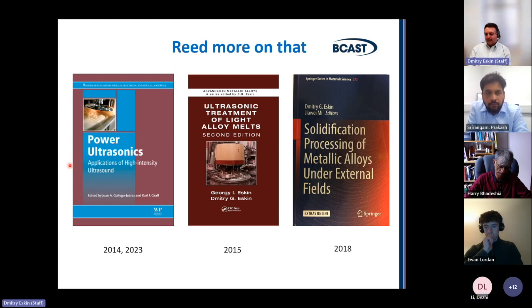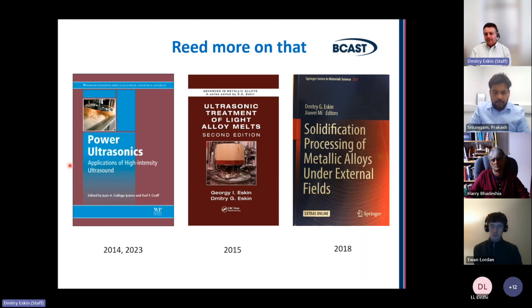Yeah. So each of the effects of ultrasound during processing of liquid or solidifying melts has its own temperature ranges where you need to perform it. When we talk about degassing, we're talking about pure liquid metal, well above liquidus. So we introduce bubbles there. That's true, cavitation bubbles. These bubbles are filled with dissolved hydrogen from aluminium. They grow while they pulsate, and then they float to the surface and release hydrogen into the atmosphere. So these bubbles are not creating any extra porosity because they're present only in the liquid metal, and they will be evacuated from the liquid metal well before solidification starts.